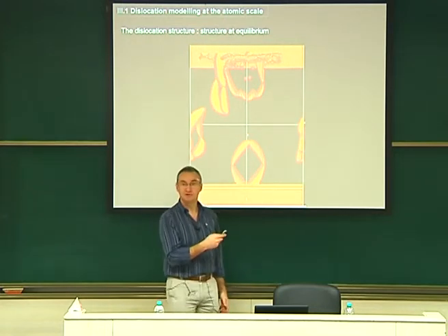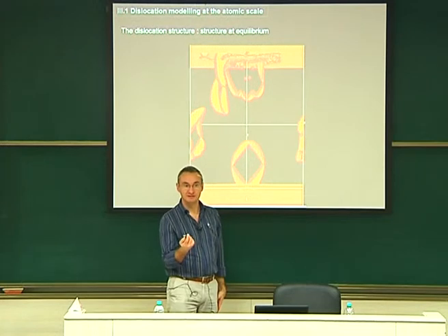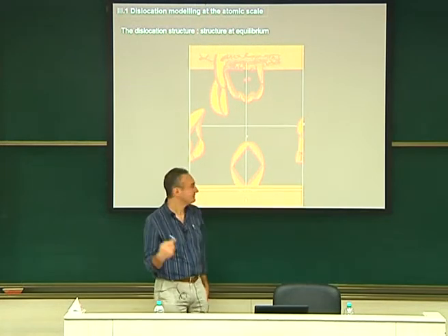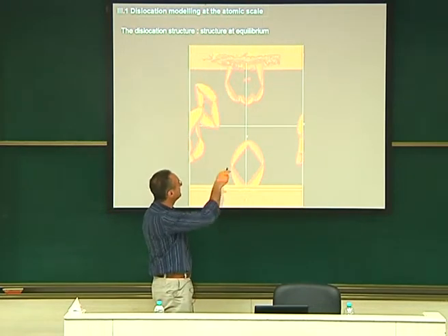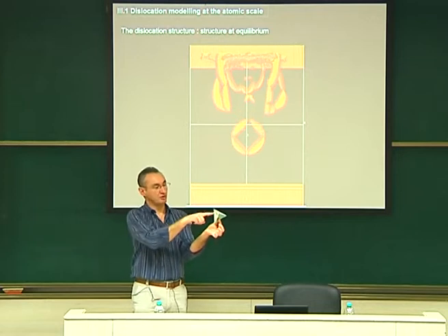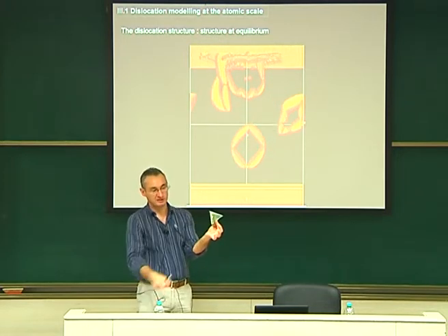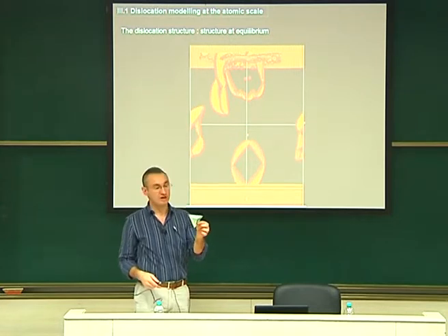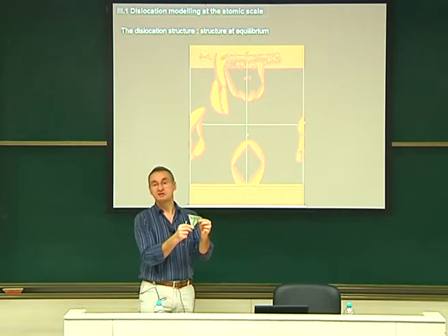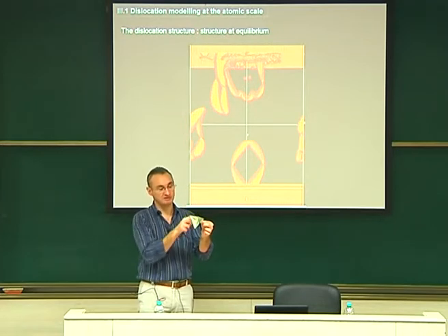So those are, what are they? Now you know this. Prismatic loops, okay? Prismatic loops, and they glide on their cylinders like that, this one, and this one, which corresponds to the 3 Burgers vectors, this one, and this one. Those are the prismatic loops going down on the 3 possible directions. Actually, those correspond to the 3 slip systems which are active. This one, and this one.